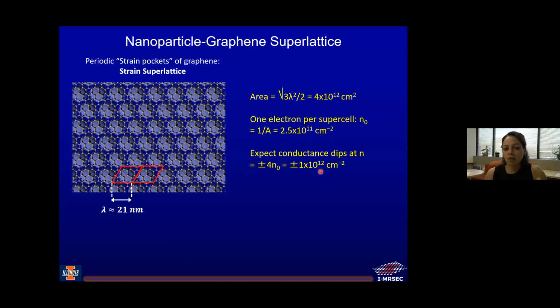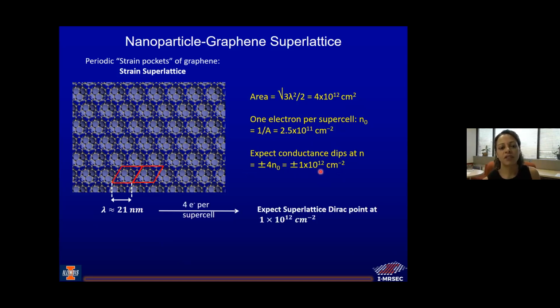Okay, so there are no assumptions here at all. We're just measuring our nanoparticle size and saying we have 4 electrons per filling site. Okay, so if we measure graphene superlattice due to these nanoparticles that are 21 nanometers, we'd expect to see superlattice Dirac points at 1 times 10 to the 12 per centimeter squared, additional dips. So we make the device and measure it.